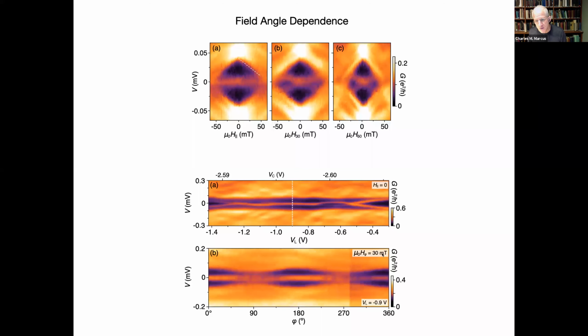So what's happening when you swing the 30 millitesla around is it's either helping magnetize or not helping magnetize the wire. In this case, it's magnetizing it the wrong way. Here, it's like 30 millitesla sideways. It doesn't like that. That's against the easy axis of the wire. It puts domains all over the place and doesn't do very much. But it is important to say that, just like any other Majorana system, it needs a Tesla of magnetic field to drive, with the right g factor, the states down from the gap to zero.